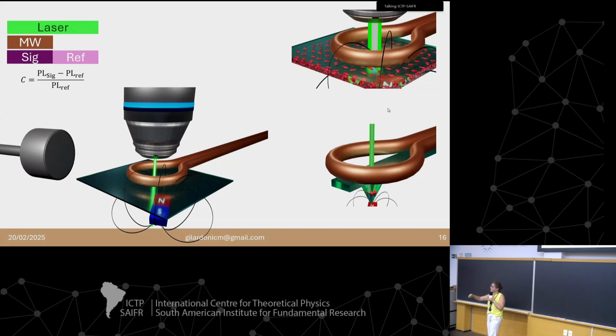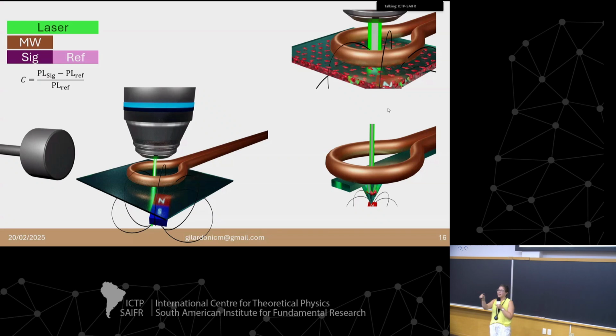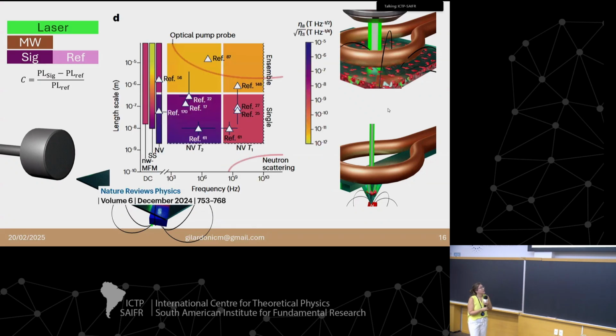a microscopy technique that looks a little bit like AFM, for instance, or MFM, if you're used to it, but where you have a cantilever, right? And that cantilever in this case is made up of diamond. And that cantilever has a tip where you have a single NV there at the end. And now you scan that tip over your material, and at the same time, you read out what photoluminescence it gives when you're driving with microwaves, right? And then from that, you can extract what is the magnetic environment at individual points in space, right?